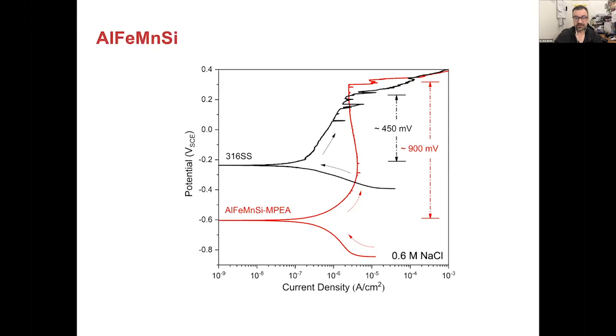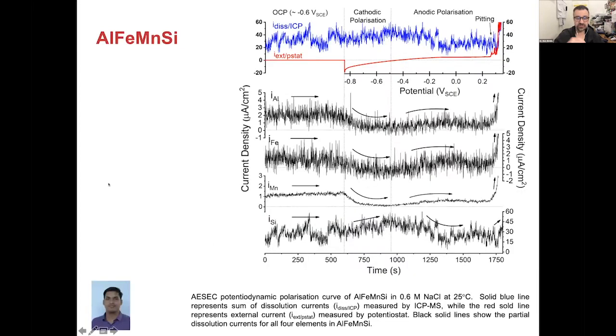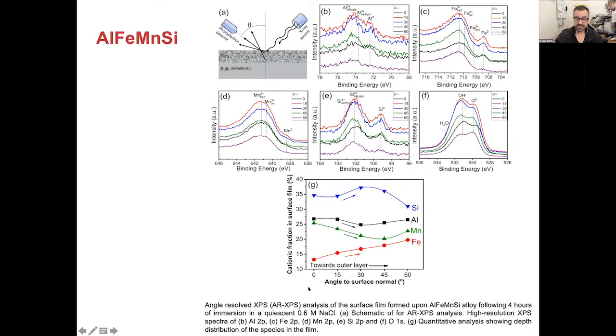And then, of course, the same questions arise. Why, right? So this is where atomic emission spectroelectrochemistry comes into it, and of course XPS also comes into it as well. So when you're doing your spectroelectrochemistry, and Sanjay did these runs, you could see that there was again incongruent dissolution. And it turned out that the most reactive element in this particular alloy was silicon, and silicon dissolved at much, much higher rates than the other elements. XPS confirms this. This particular data shows the cationic fraction in the surface film using angle resolved XPS, and it shows that there's much more silicon in the film as opposed to aluminium, manganese and iron, which one normally thinks of as the least corrosion resistant element, perhaps, in this ensemble of elements, actually was being oxidized at the lowest rate of all.